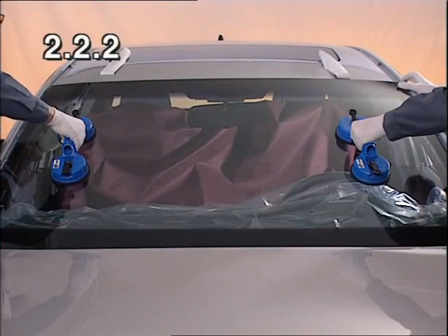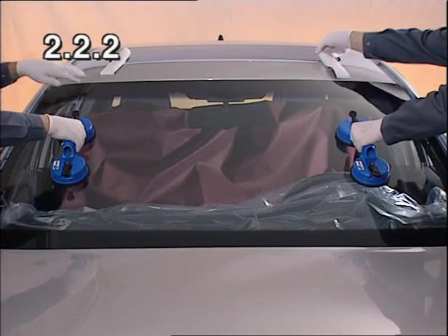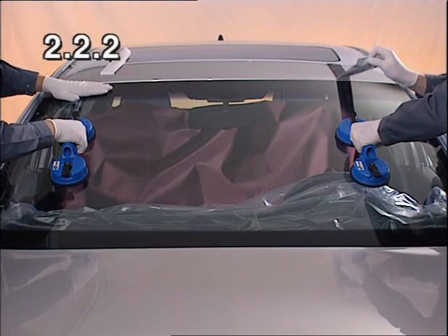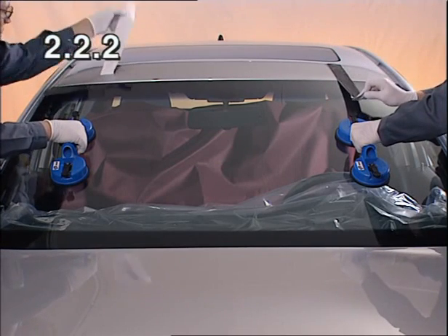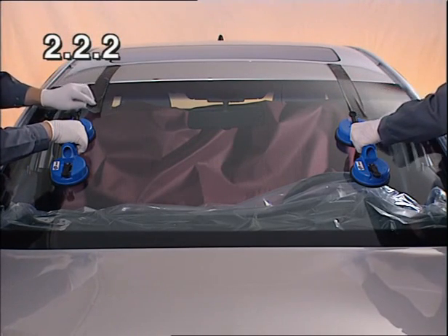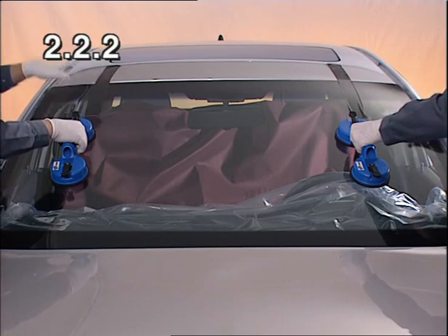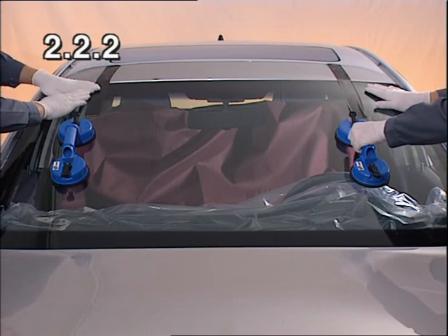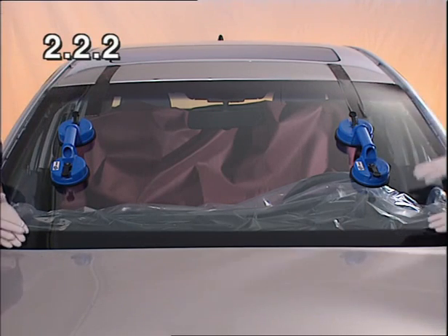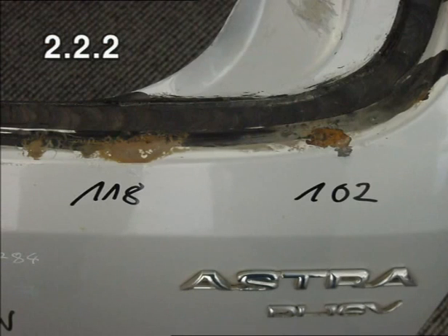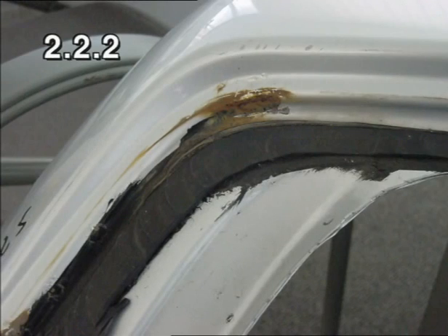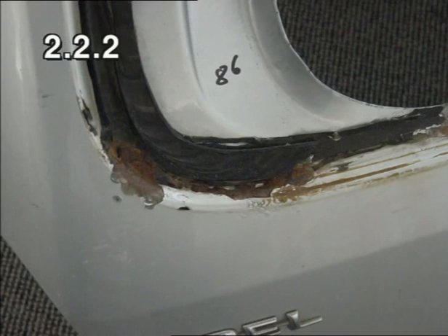A new adhesive technology has produced a high level of crash safety without the adhesive having to be fully cured. In addition, the adhesive is non-conductive. In other words, it insulates, which prevents corrosion on a metallic base material. Repair trials with conductive adhesives and universal primer applied to areas of bright metal led within a short time to serious corrosion damage.